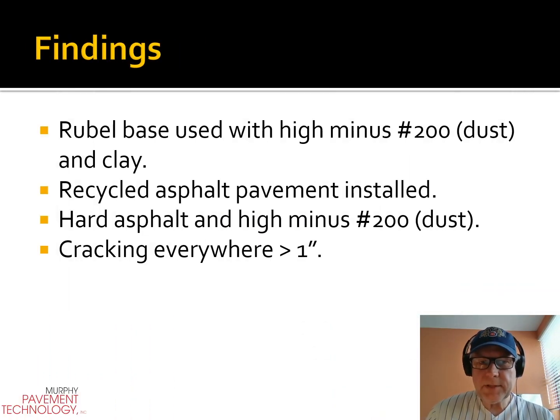And then the forensics actually dug into the foundation and found that the slip sheet was adequately specified, but the product installed was not what was specified. It ended up being rubble with a high amount of -200s and clay. It became very stiff, and when moisture got in, it cracked. The cracking of the foundation actually reflected through the asphalt. The asphalt wasn't the greatest either. It had a really high amount of recycle, very high dust, and poor density. So a lot of things went wrong on this project. It was a good design. The execution on it just was not proper.